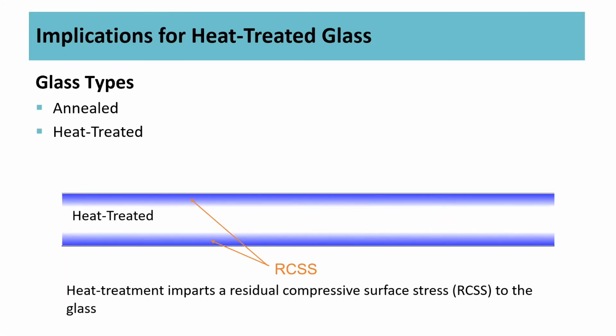When we heat treat glass, we're heating it up to a near melting point or almost softening point, and then we cool it down very quickly. Depending on the rate or the intensity of that cooling, or quenching, it imparts a RCSS, a residual compressive surface stress, into the glass, and the magnitude of that has to do with that cooling process. One of the things we need to know to do a before and after with our polished glass is what the actual RCSS is on our piece of glass.